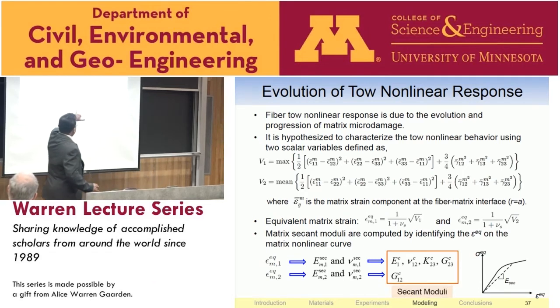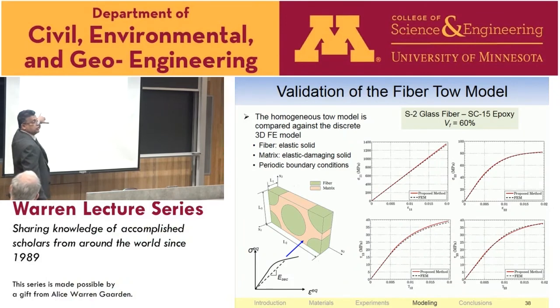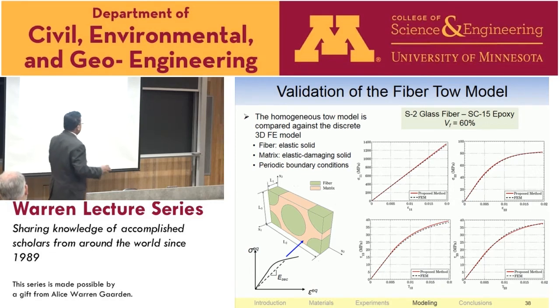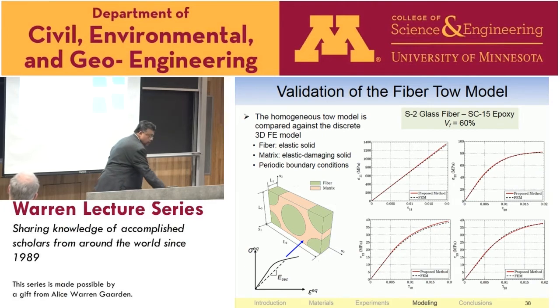So when we do that for, say, a hex pack unit cell, we use our model and a full 3D model. You can see that the nonlinear response is captured very well. The difference is the full 3D finite element model, if I did it finite element within a finite element multi-scaling, it would have taken forever. But now the subscale calculation is done analytically, so it speeds up your calculations very much. Still multi-scaling.